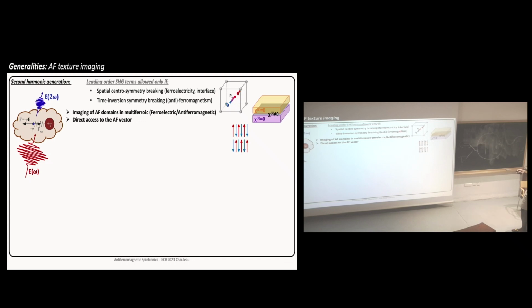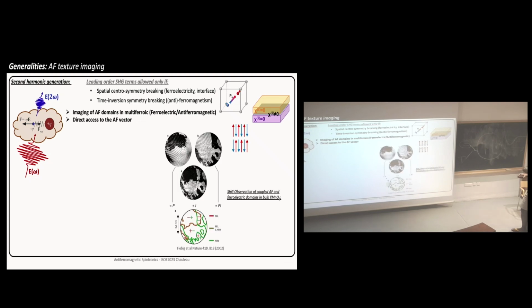And on top of this, you can add the time inversion symmetry concept. That was, for example, done in the pioneer work of Manfred Fiebig, where they managed to nicely image this one, which is the ferroelectricity. This one is the coupling between ferroelectricity and antiferromagnetism, and they managed to deduce the antiferromagnetic pattern. That was done in bulk YMnO3, which is a well-known multiferroic.